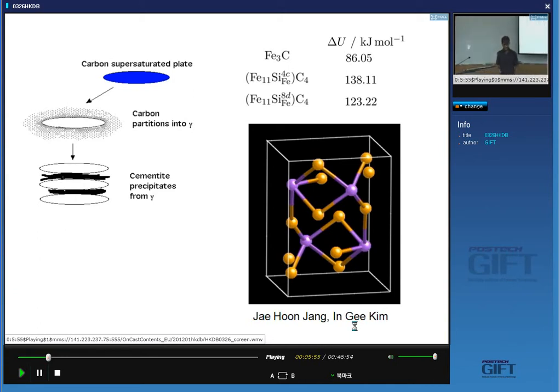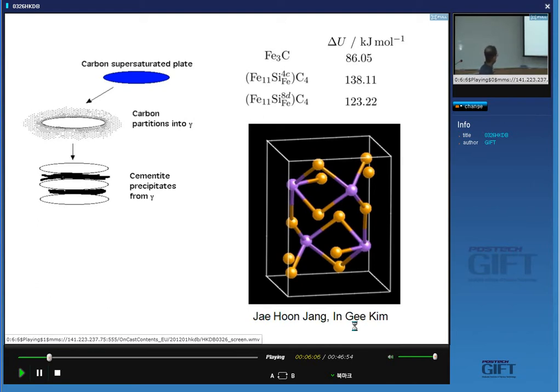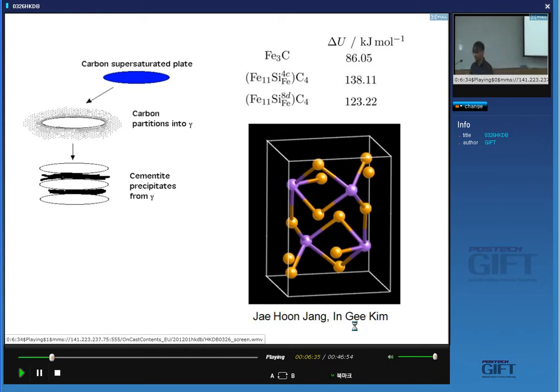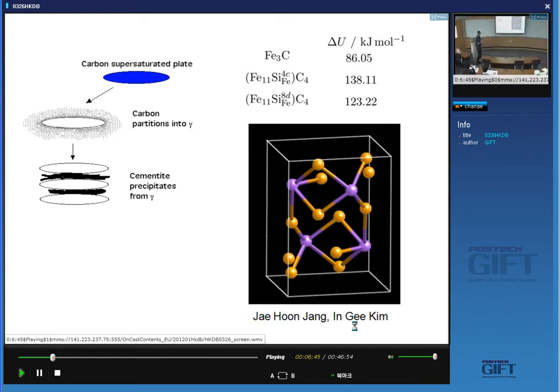The mechanism involves partitioning of carbon from the supersaturated plate into the remaining austenite — it is the precipitation of cementite from austenite that we have to stop. If you look at the solubility of silicon in cementite, it is almost zero. When you form cementite at a low temperature, around 400°C, there is no opportunity for silicon to escape while the cementite is growing. Therefore, the cementite is forced to absorb any silicon in the steel, even though it does not want it. Once silicon is forced into cementite, its energy increases and it becomes less stable.